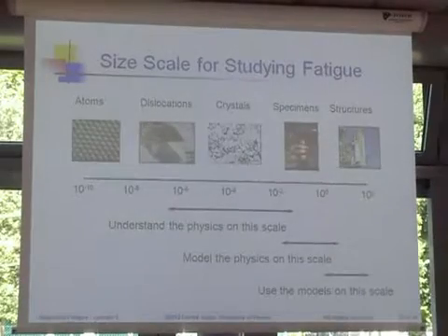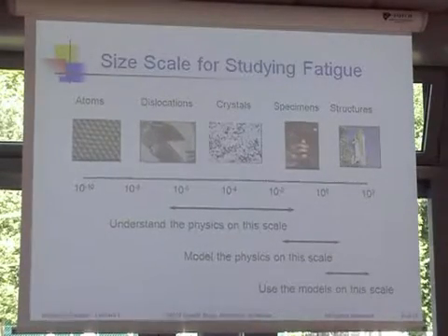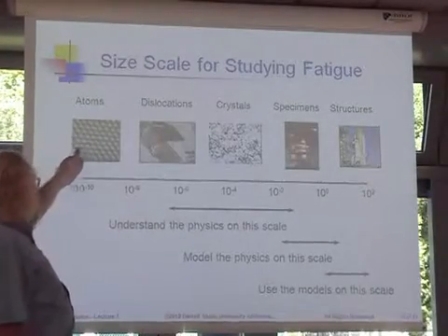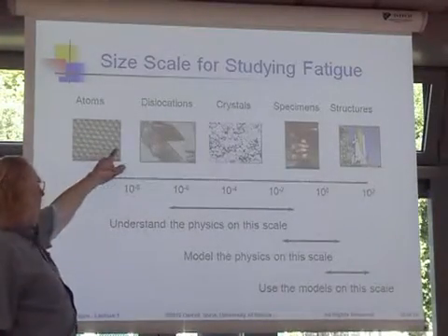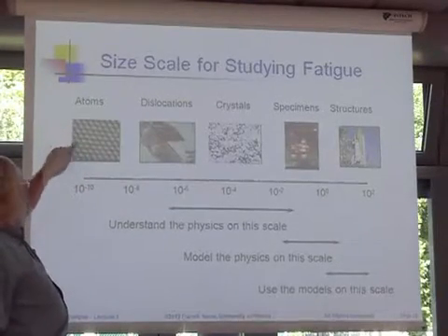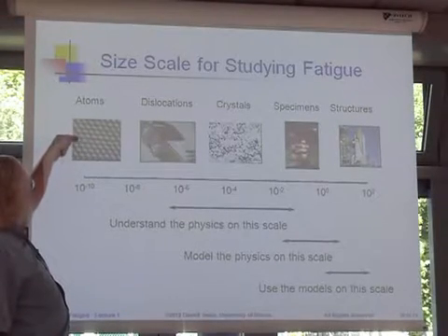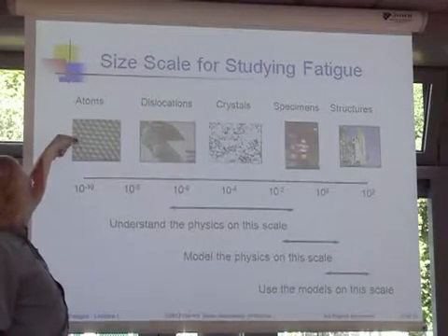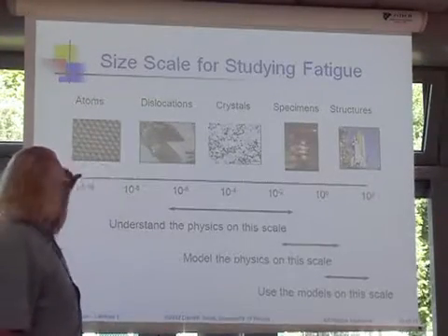And you can imagine that now in the atoms, that what I show here is an array where there's an atom in every place. But imagine what would happen if there were a missing row of these atoms. And if there were a missing row of these atoms, then if I wanted to move something into this missing row, I could move the row behind it into here. That would leave this row missing, this one in, this one missing, and so on, one row of atoms at a time. And that's really what happens.